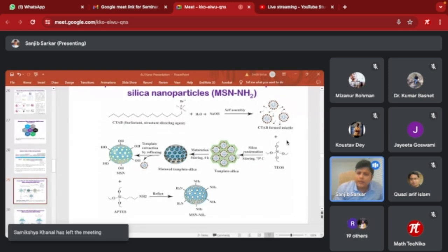And when we add only vitamin K, GLUT4 expression was increased a little bit. However, when we use vitamin K loaded nanoparticle, the GLUT4 expression is significantly higher. That means the same amount of vitamin K cannot increase the GLUT4 level in the cells. On the other hand, the same amount of vitamin K, when it is in the nanoparticle, increases the amount of GLUT4. That means the nanoparticle also increases the bioavailability of the vitamin K.